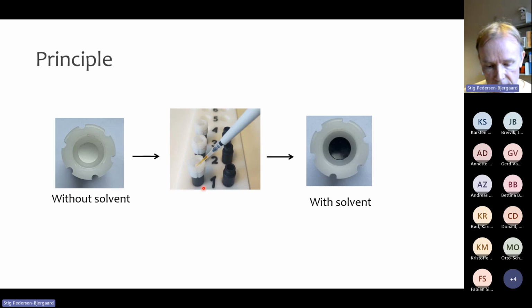The liquid membrane that separates the acceptor and sample solution is a key element in EME. And the liquid membrane is prepared by pipetting a few microliter organic solvent into a porous hydrophobic membrane. And you can see the dry membrane here. And when we have pipetted the organic phase, it becomes like this. It becomes more transparent. And the organic solvent, when we pipette the solvent to the surface of the membrane, immediately goes into the pore volume, and it's immobilized and held there by capillary forces.